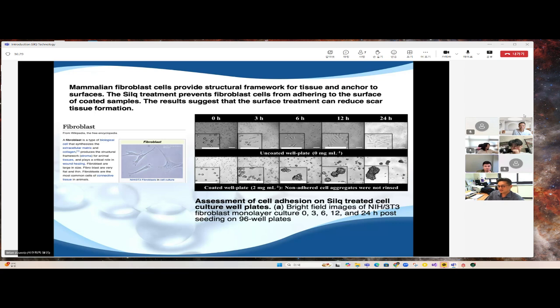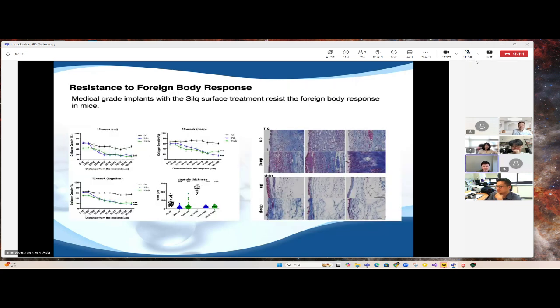Okay, great. So I got one more slide on the fibrosis for you, actually. So the question timing was very good. We implanted silicone discs, little sheets of silicone, in mice for 3 months. In the top 6 images, this is the tissue in contact with that silicone disc. The silicone material was on the left of these images. We stained the tissue with a stain specific that binds to collagen. And so what we're doing is we're observing collagen growth, which is an indicator of fibrosis on this tissue. And so you can see here in the top 6 images a lot of blue, a lot of collagen. And that's that capsule forming, that scarring forming around that device.